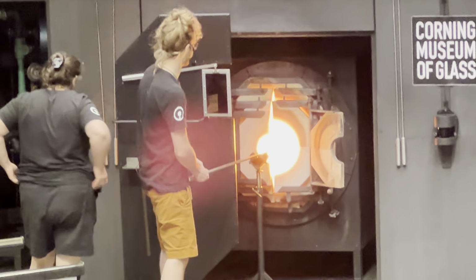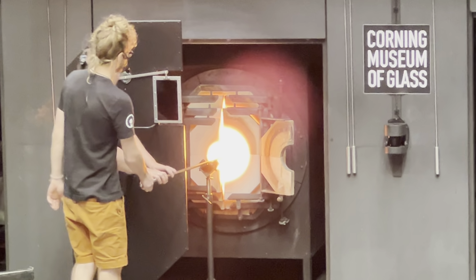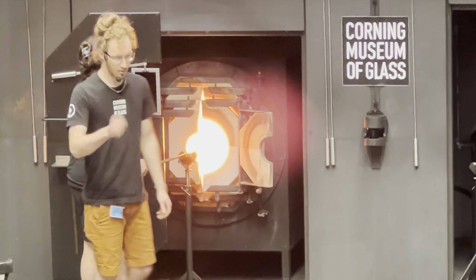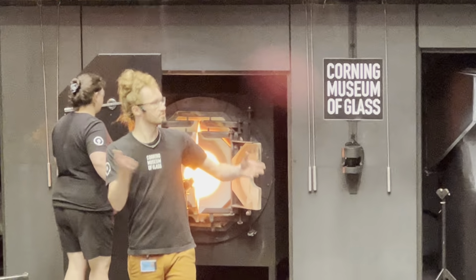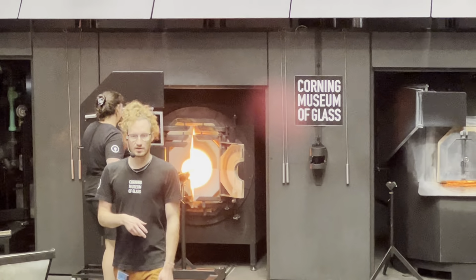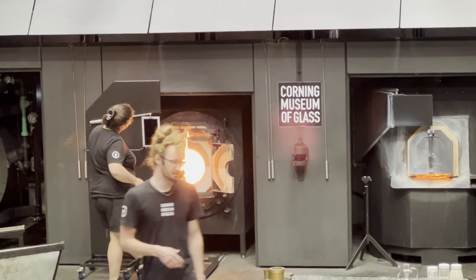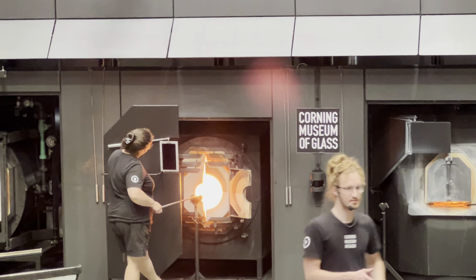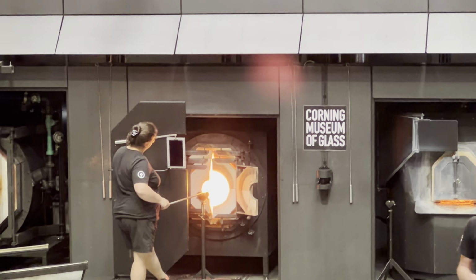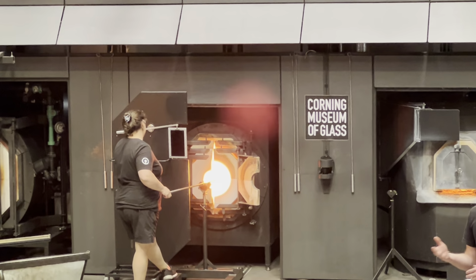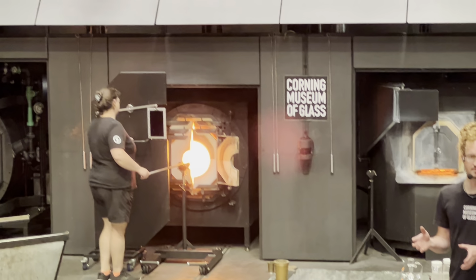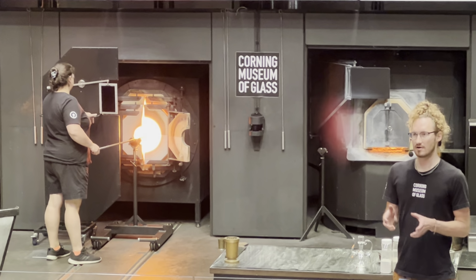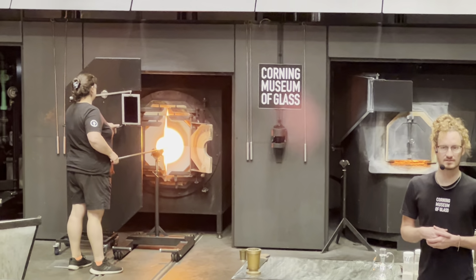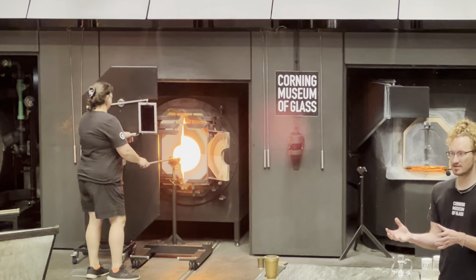Nicely done. Now the other thing that can happen is if we let this get too cold, when we go to break the glass, it'll shatter, just like glass breaks at home. So we lose a lot of things in our early days as glass makers. Nothing is telling us the temperature of the glass aside from our experience. So we make a lot of really bad guesses in our early days as far as what the temperature of the glass is. So it broke because it was cold.